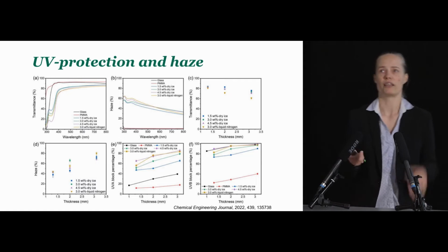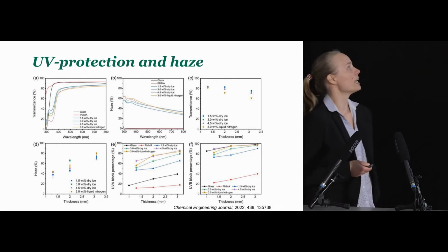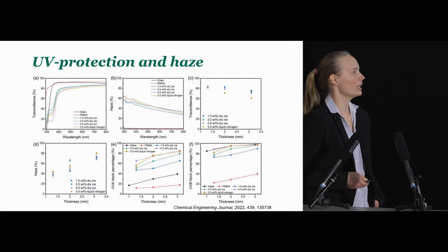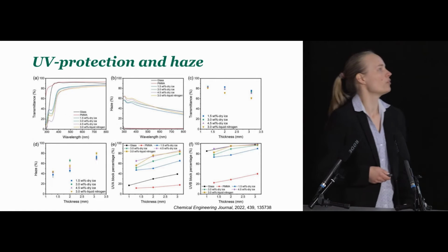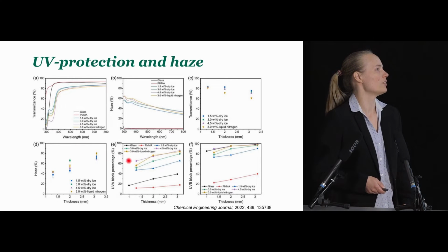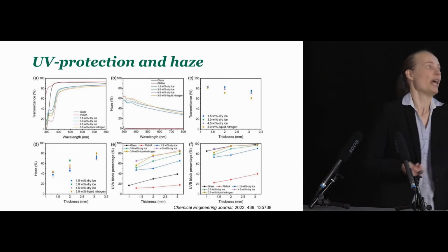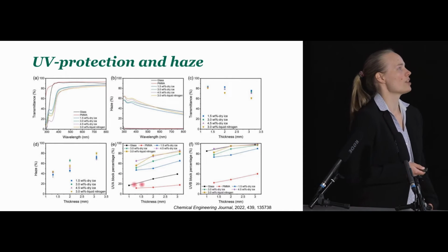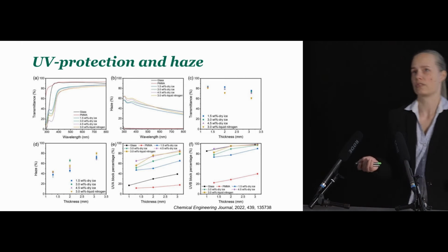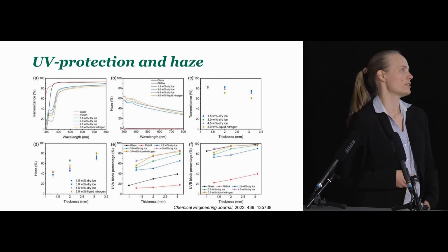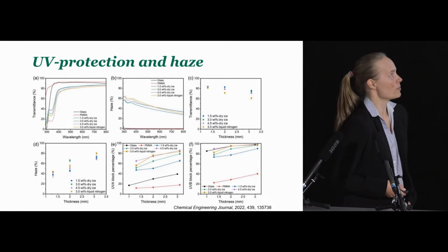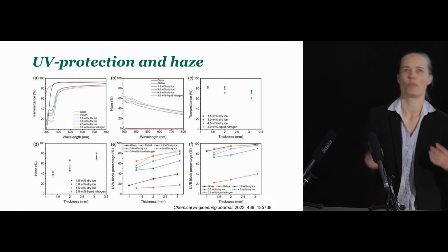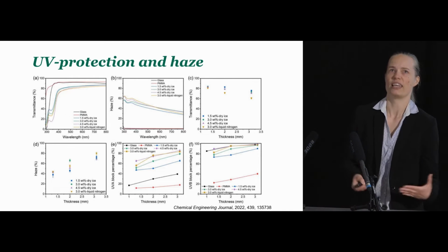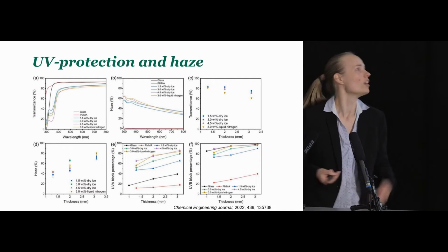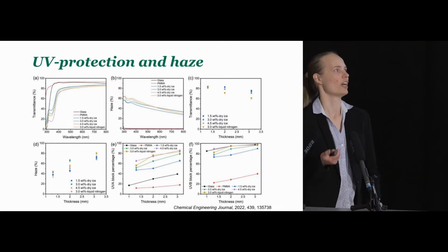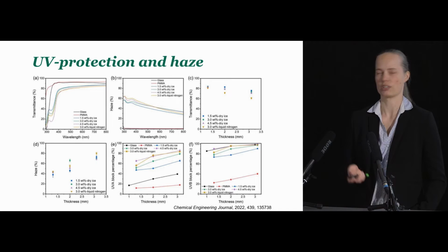Another additional benefit that comes from applying pectin is that pectin has quite a nice absorption in the UVA and UVB regions. So if we think about the UVA blocking capacity and UVB blocking capacity of these films, especially in the UVA region, we can reach much higher UVA blocking as compared to a simple glass device or simple PMMA here. So this is one of the examples where if we take a plant-based polysaccharide, we can actually reach added benefits over the advantage of being sustainable and using a biosourced or bio-waste-sourced material.